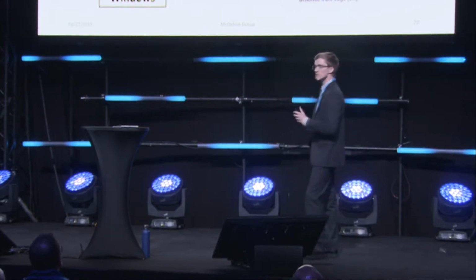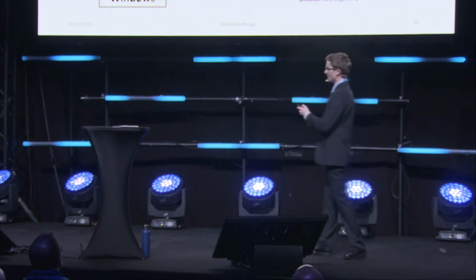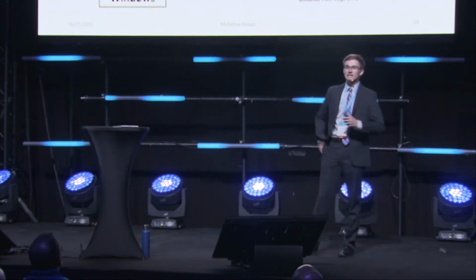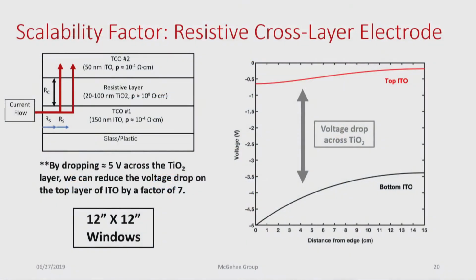So by tuning the material properties of these three layers, and applying a potential to our bottom TCO, we are able to drop a significant amount of voltage through our resistive inner layer. Even though our bottom TCO is still experiencing a significant voltage drop, we can now drop a lot of this voltage through the inner layer, such that our top TCO, the layer that's actually exposed to the electrolyte within our window, only experiences a minimal voltage drop of about 0.3 or 0.4 volts, which is the voltage tolerance needed to switch uniformly for our windows. This will allow us to start switching uniformly on a foot scale, and we can further tune these properties to even reach up to a meter squared scale.